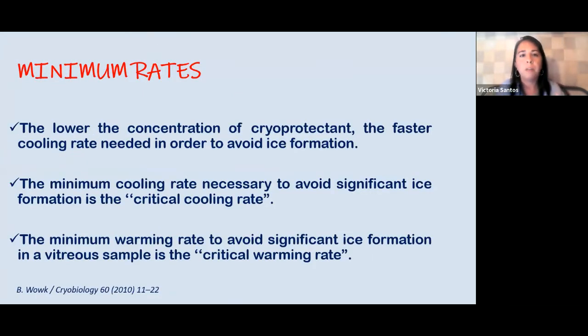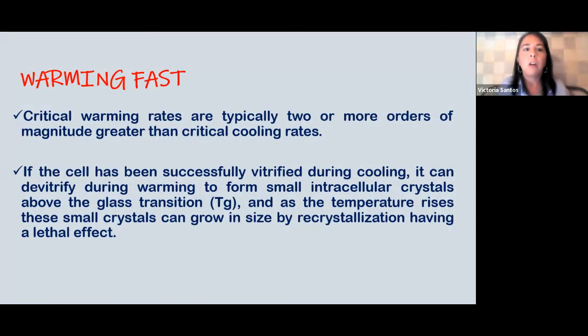So, what are the minimum rates? The lower the concentration of the cryoprotectant, the faster you need to cool in order to avoid ice formation. The minimum cooling rate necessary to avoid significant ice formation is the critical cooling rate. The minimum warming rate in order to avoid the devitrification of a vitreous sample is called the critical warming rate. The critical warming rates are typically two or more orders of magnitude greater than the critical cooling rates.